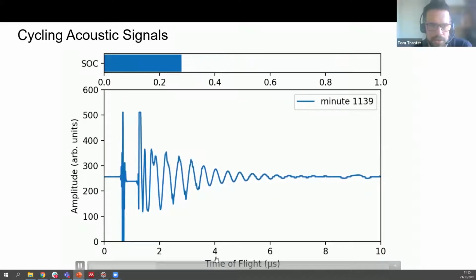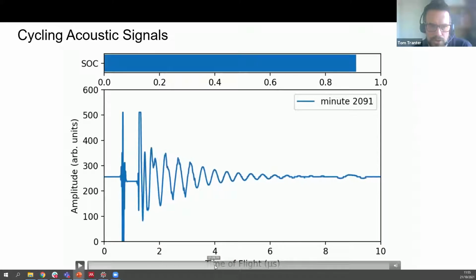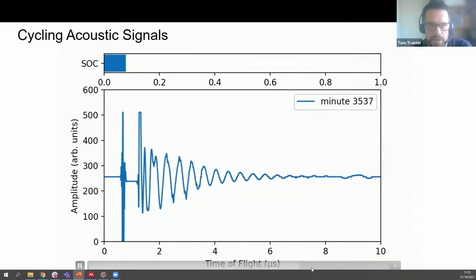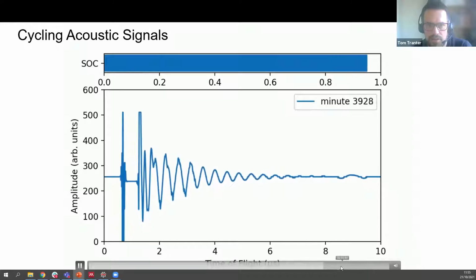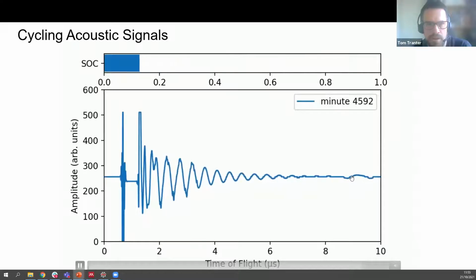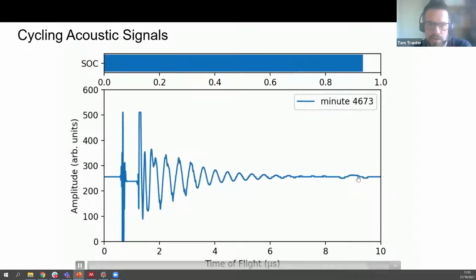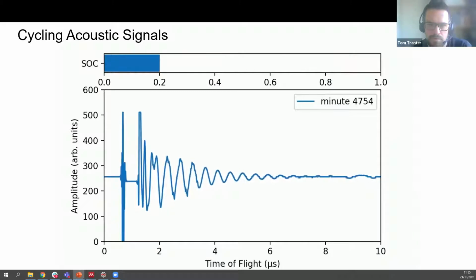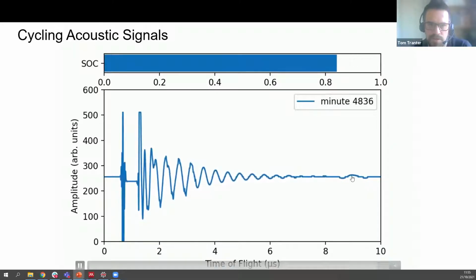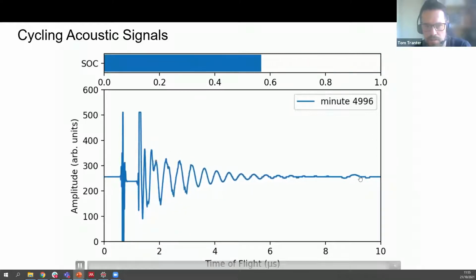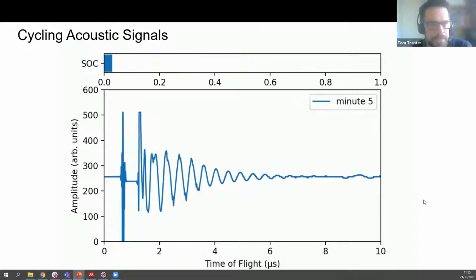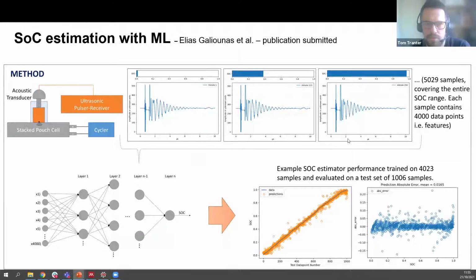But as this is going quite slowly, you can see the peak is not shifting too much. If you go later on, we're now at higher discharge rates, and you can see this peak is really moving around. And this is a combination of maybe more stressful material changes, but also increased temperature. As you discharge and charge faster, you're going to be producing more heat. And so this is work that's been submitted, but not published yet.